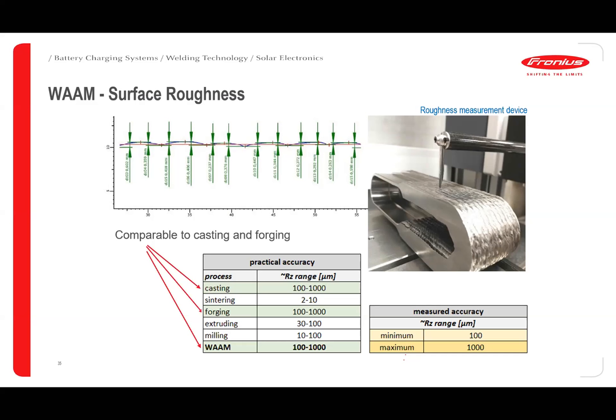And our experience is we have used different diameters of filler wire. When we use a lower diameter of filler wire, we are able to have more control on the surface roughness, your ridges and valleys, that is the undulations, which can be further controlled when we do a study with the help of lesser diameter wires. I'm talking about the filler diameter which we are using.